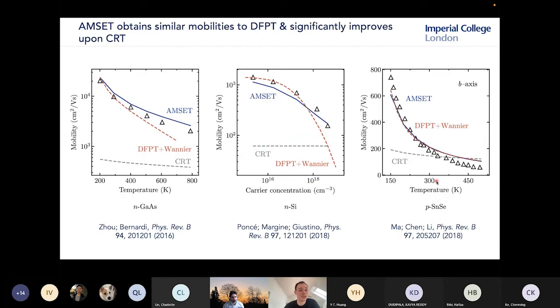This is just some more comparisons to show you that we actually perform pretty well compared to DFPT plus Wannier. This is three materials: gallium arsenide, silicon, and tin selenide. Here I'm showing AMSET in blue and these DFPT plus Wannier results in red, and again, experiments shown by the black triangles. You can see that basically we're really in the ballpark of DFPT plus Wannier across the board.